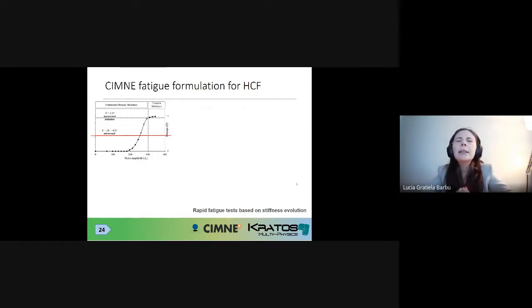In the experimental analysis, they were able to detect an increasing level of structural damage. What I mean by this is they computed a specific damage parameter based on the evolution of the stiffness. This is somehow to be understood as a macro structural damage.